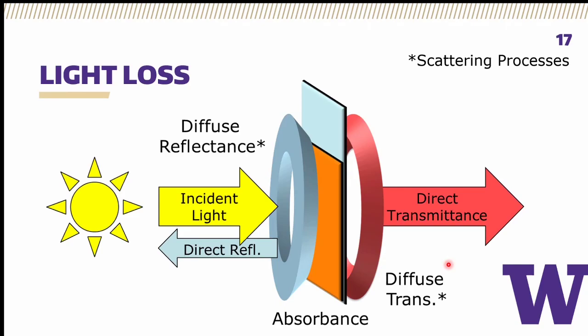Yeah, no, that's something I tried very hard to do. The problem is it's impossible. It's very difficult. And I did a lot of different things to try to make this happen, through thinning the layer in a number of different ways, like spin coat speed or concentrations, or even compositional changes and things of that nature. But no matter what, what I found is when you make your layer thinner, you introduce a bunch of pinholes. And the pinholes, for those unfamiliar with PVs, those are device killers. And so your device goes to basically zero efficiency, unfortunately. I mean, not actually, but it's very difficult to come back from that.